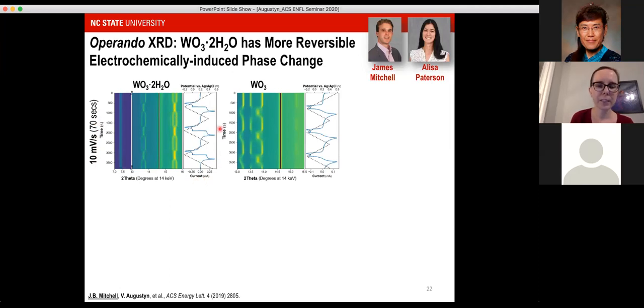And over here our input is this linear potential sweep that's reversed. That's the 10 millivolts per second. The blue curve, that's the current response from the material. And what's shown here is the X-ray diffraction pattern, kind of looking down. So you're looking down at the X-ray diffraction peaks. This is the interlayer spacing. And these are these two other peaks that before we saw changing in the ex situ X-ray diffraction, but not their dynamics. On the right-hand side is the anhydrous tungsten oxide material.